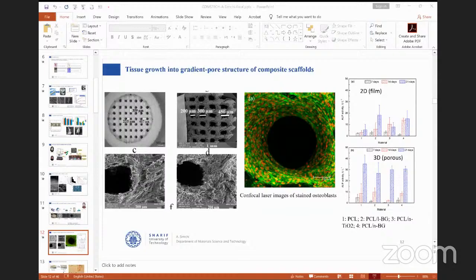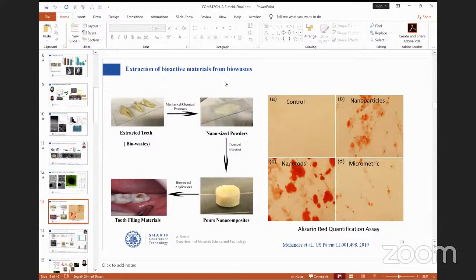And interestingly, we did an ALP analysis and showed that the 3D pore structure works even better than a flat surface. So when there is a curvature in the pore structure, the cells stick better to the system and grow inside the pores to generate a tissue, for example, a bone tissue in the system. However, we used nanoparticles of bioglass, and we found that the bioglass is not very stable inside the body, and sometimes we have some kind of cytotoxicity. Therefore, we thought it's better to use hydroxyapatite, but as you know, hydroxyapatite may not be as active as nanoparticles.